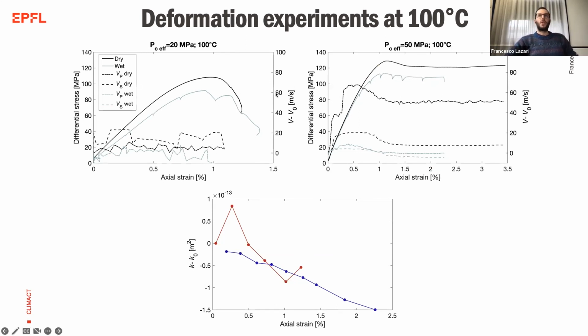And we can see that in both cases, the black curve here, which is the dry experiment, has a higher stress than the wet curve, which means that the dry sample is stronger than the wet one, both in the brittle and in the ductile field. On the bottom panel, we can also see the permeability variation of the two wet samples. And we can see that with increasing strain, so with increasing deformation of the rock, we are decreasing the permeability of the sample because of closing of pores, mostly.